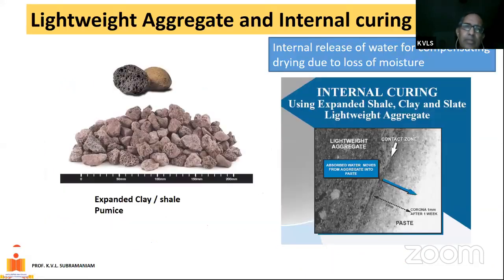Now, the other things we're also using to cut down on the shrinkage of concrete, which are basically water reservoirs inside concrete in the form of expanded clay and shale or pumice, which are all porous rocks, which basically act like water release inside the concrete. So these are all things that we are looking at in terms of mitigating cracking in concrete from different reasons. And typically, mostly concrete cracks in service because of load effects. Those are taken care of in the design, but also from material effects like shrinkage. So I have admixtures, I have other additives that I can add now to take care of cracking in concrete.